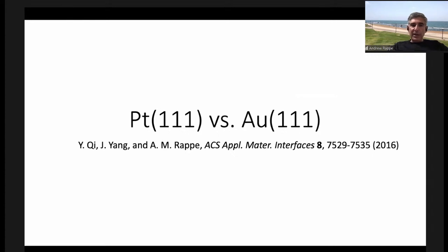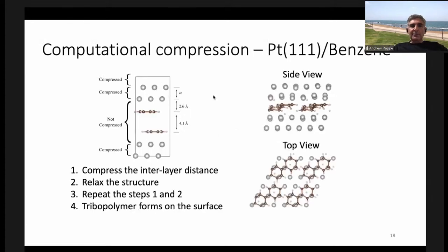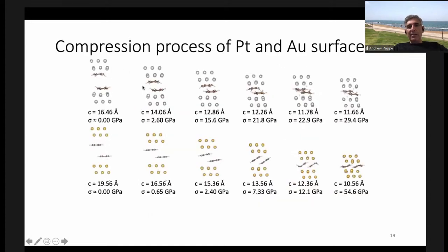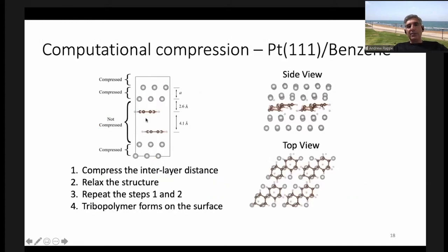Okay, so let's first compare platinum and gold. So here is our computational paradigm. We propose that the reactants that form the tribopolymer are benzene. You can see the benzene from the side here, and it's in between two metal contacts that are in the process of closing. At each step, we compress the interlayer spacings in the metal, and then we allow the metal to relax, and that compresses the molecules that are trapped in here.